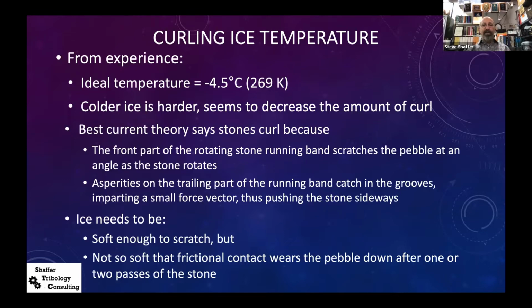If it rotates too fast, it's a very steep angle. If it rotates slowly, it's a mild angle. And the asperities on the trailing part of the running band, they catch in those grooves, in those scratches, and this imparts a small force vector laterally, pushing the stone sideways. So the ice needs to be soft enough to scratch, but not so soft that the frictional contact wears the pebble down after 1 or 2 passes of the stone. And in fact, you'll see this change over the course of a game, that the amount of curl changes and the speed of the stone changes because the pebble is being worn down after repeated contacts.